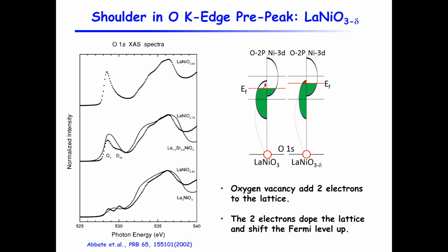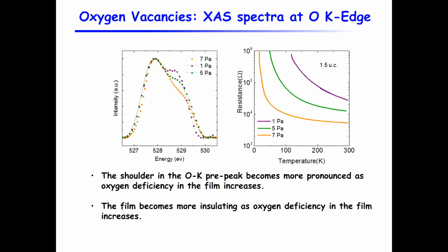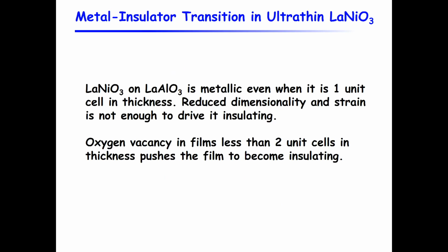If you have, this is lanthanum nickelate, O3, 2.75, and this is oxygen 2.5. And you see this feature become more and more pronounced. And that's what we have seen when the film becomes thinner and thinner. Then we grow, this is a 1.5 unit cell film grown at different oxygen pressure. Again, we see that when the pressure becomes lower, this feature becomes more pronounced. So that corresponds to the thickness when we see this dramatic increase in the resistivity and the insulating behavior. So what we propose is that oxygen vacancy is important in this metal insulator transition. Right?